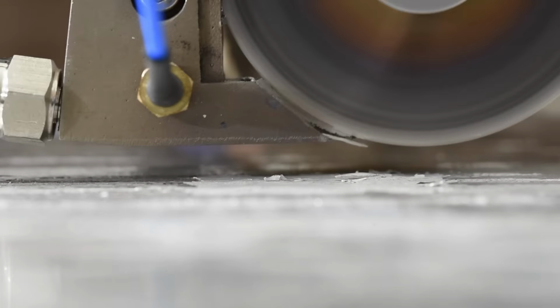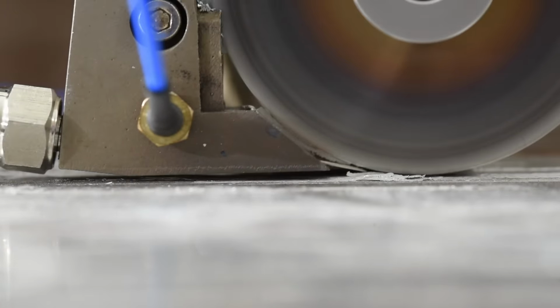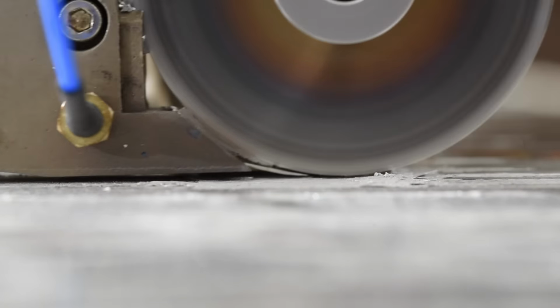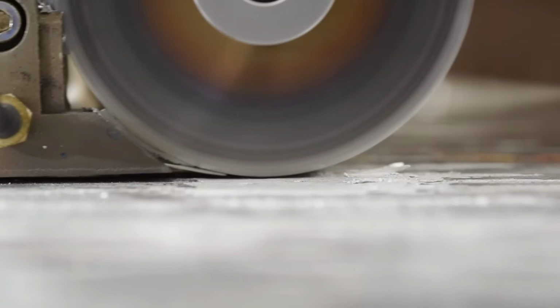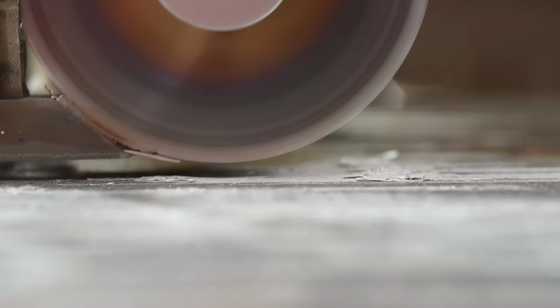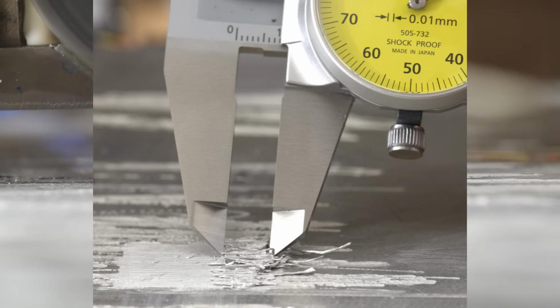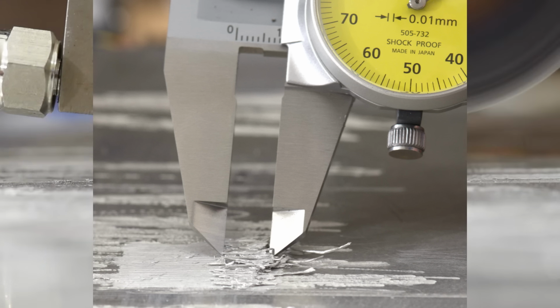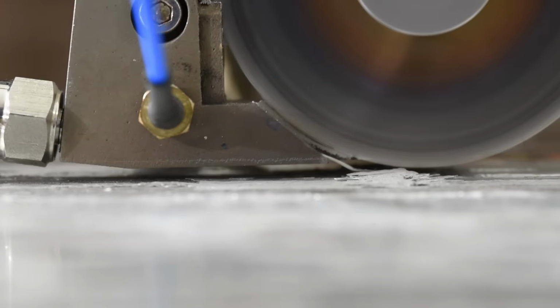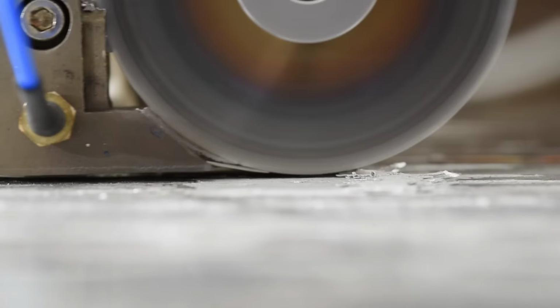So naturally, the most obvious thing to do is to try and do raster printing line by line, each line stacked roughly with a 50% overlap or 30% overlap or 70% overlap with the previous line until we could build up a line in the y-axis by printing multiple rasters along the x, hopefully using the minimum induction length or the shortest possible starting line length that we could feed and bond reliably with the wheel. It turns out that that minimum bond length is somewhere around 4 to 7 millimeters, perhaps less if you're craftier and have better control over volume feed and the rate at which the wheel is spinning and the temperature of the wire when it goes down.